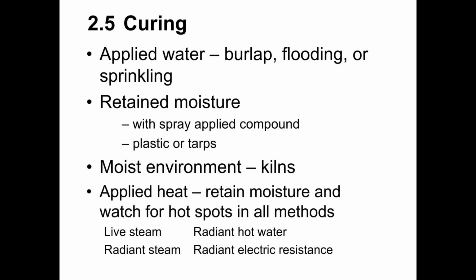All right, curing, and then we'll talk a little bit about economy and wrap up chapter 2. So for curing, the requirements are going to vary depending on the mix design that is used and the product that is being cast. If we have a mix design that incorporates silica fume, then we may need to have water applied to the unformed surface just to make sure that that surface does not dry out and we don't get plastic shrinkage cracking. We can do that by covering the surface with burlap and then soaking the burlap. We can flood the surface, or we can keep a sprinkler on that surface so that we maintain 100% moisture on the surface.